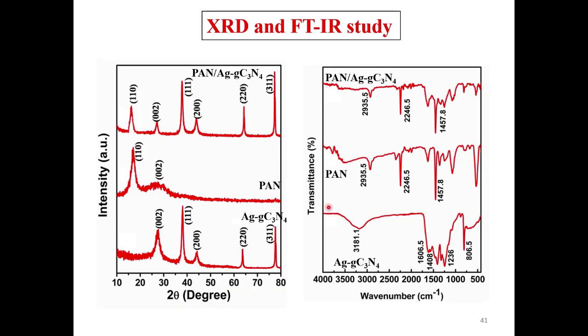This is the XRD and FTIR. XRD and FTIR are self-suggesting that there is a formation of a pure form of polyacrylonitrile silver grafted carbon nitride nanofiber. Here is the XRD of AgGC3N4, PAN nanofiber, and PAN AgGC3N4 nanofiber. Both the peaks are combined into this single XRD pattern, itself suggesting that formation of PAN AgGC3N4 nanofibers is there.